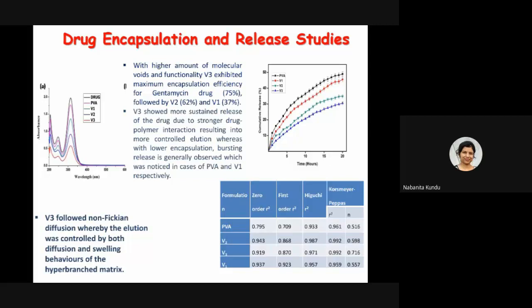This is the first application where we have entrapped the drug molecules within it, and we have studied the release of the drug molecules in vitro, not within the body, in the Franz diffusion cell. So this is where we entrap the drug within it, and we see the release at a constant rate. This blue one is the lowest one, where we have used the most hyperbranch structure for encapsulation of the drug molecule. There we see that the release rate is the slowest. So you can get a more sustained therapeutic effect when you apply this kind of polymer.